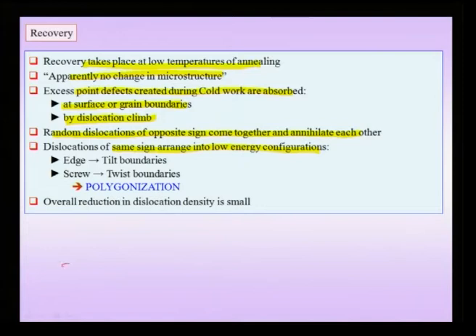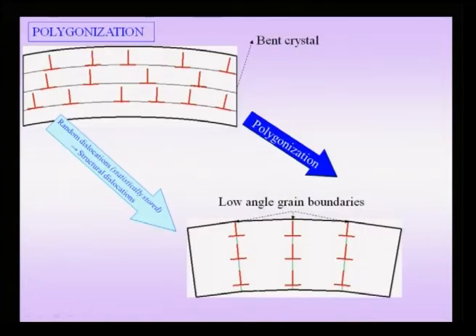But if you talk about defects, the pronounced effect is on point defects, and of course this may include self interstitials. And if you are talking about dislocations, there is a lesser effect on dislocations. What happens is that dislocations of opposite sign come together and annihilate each other, that means they come towards each other, and finally you land up with a configuration in which you have a full atomic plane, that means no dislocation. Additionally, if you have dislocations of the same sign which are lying on different slip planes, then we will see in the next micrograph that they can come together to form low energy configurations like low angle grain boundaries. So, we will come to this slide in a little more detail.